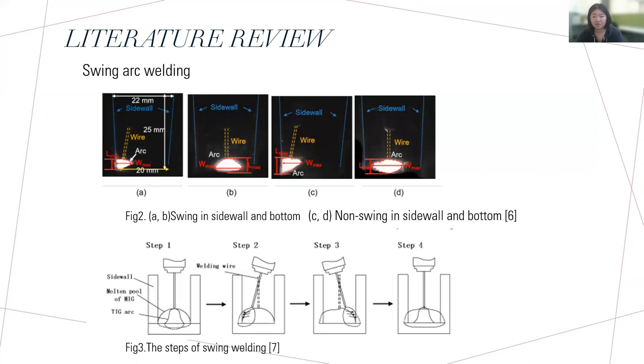Conversely, the penetration depth of the groove bottom decreases with a wider oscillation width, but a width that is too narrow increases the risk of sidewall defects.